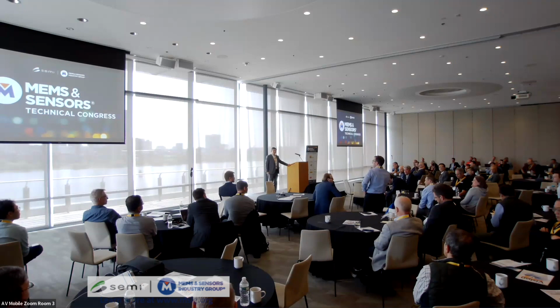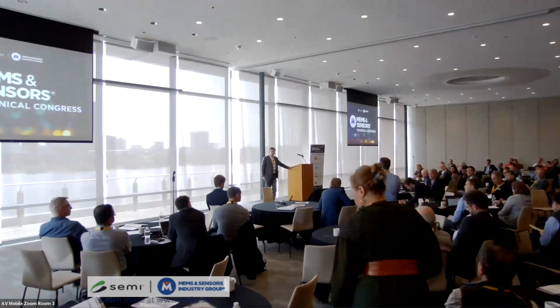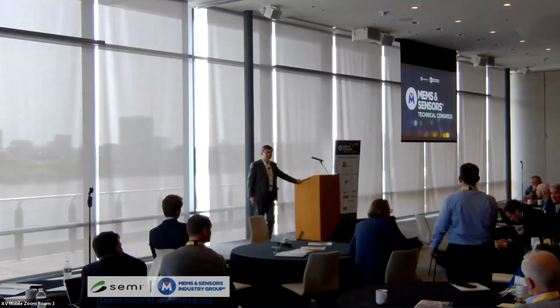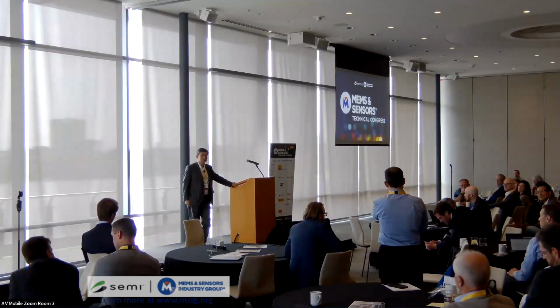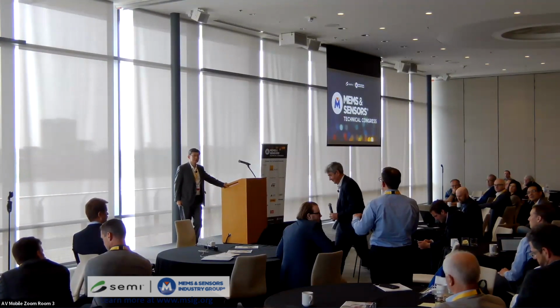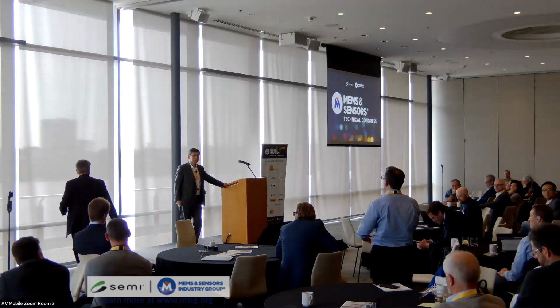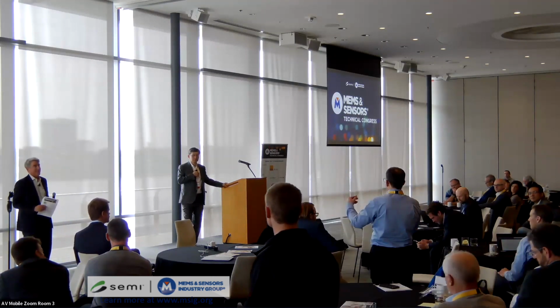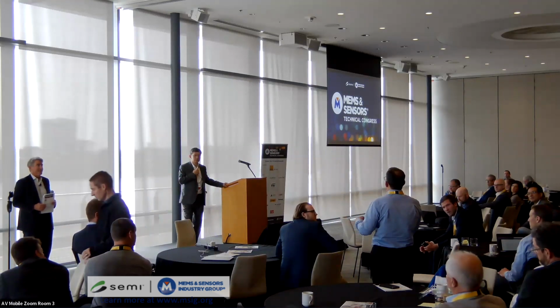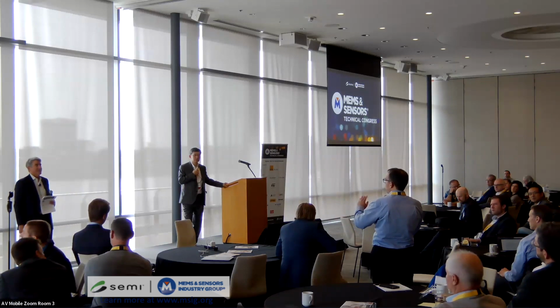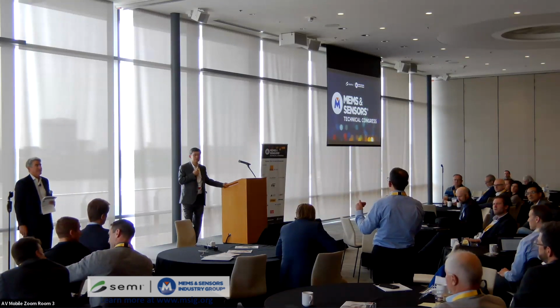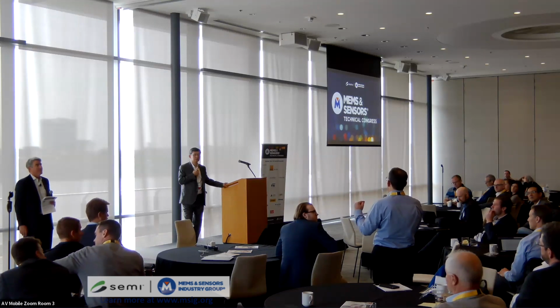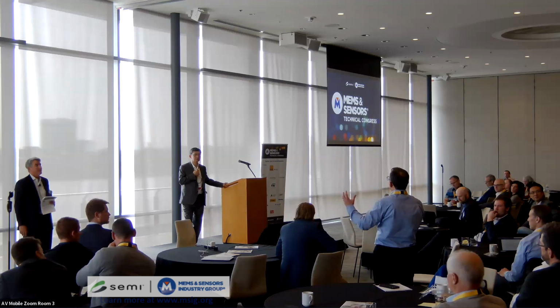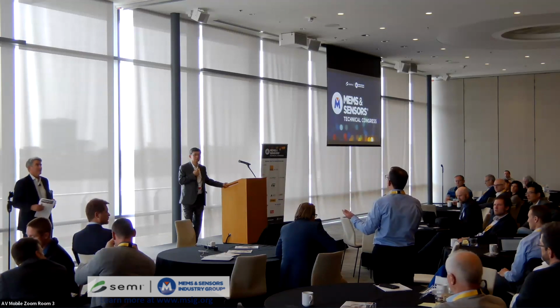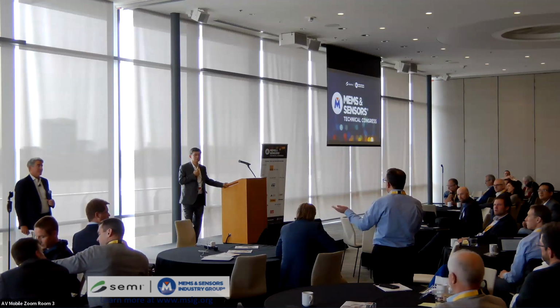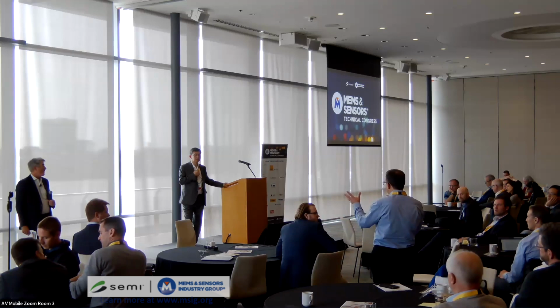Hello, Karel Crote, C2MI. A little question. Well, we did use fused silica, borofloat, or all those glasses for microfabrication. And the first question was to the point. It's one issue to make sure that we don't have any cross contamination throughout the fab. The other issue we have is actually in all the etching tools. We're having electrostatic chucking problems. I'm just throwing you a curveball. Are there any tricks that you have found to have a substrate where you can still have that attraction, without having to coat the exterior? You mentioned having a coating layer on top, so that we can still use electrostatic chucking for etching or for any deposition in high vacuum systems. Do you have some tricks up your sleeve?